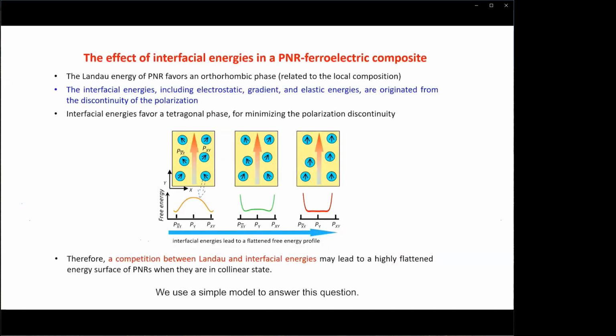We use a simple model to answer this question. As shown in this figure, there are some orthorhombic polar nanoregions embedded in a tetragonal ferroelectric domain. So some interfaces are present in such a heterogeneous system. Because of polarization discontinuity around the interfaces, there are considerable interfacial energies in this system, which include electrostatic energy, polarization gradient energy, and elastic energy.